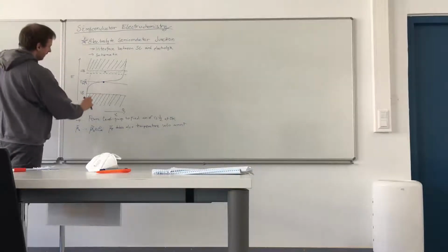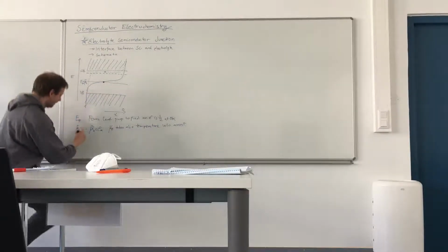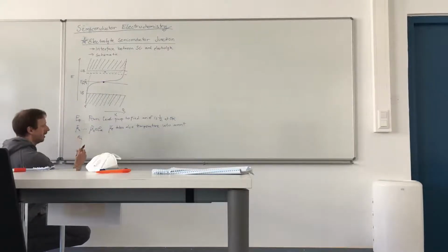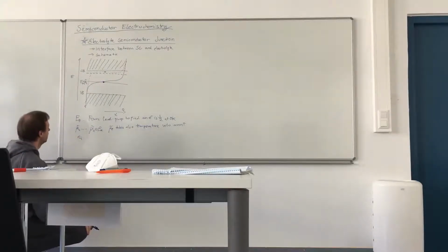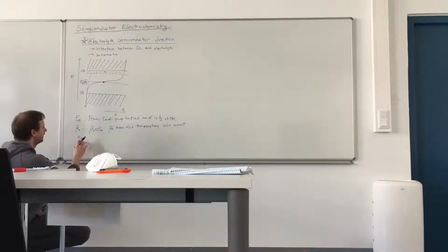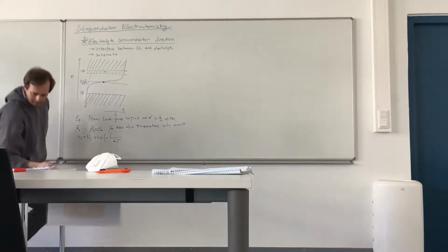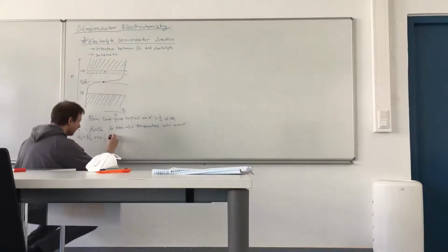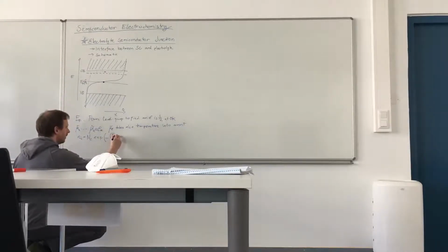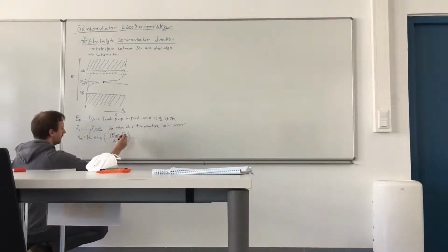So for the undoped case, the amount Ni of electrons in the conduction band, where I denotes the intrinsic case, is equal to the density of states times some exponential of (E_C minus mu tilde electron intrinsic) over kT. Intrinsic means for the undoped case.